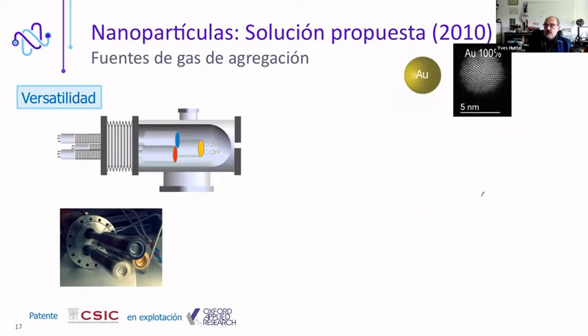But this was too limiting, really. Then we faced the problem of combining different elements inside a single cluster source. That was the first technological limitation we were facing, and we had to find a solution for that. We came up with a solution that consists in replacing the single magnetron inside the aggregation zone with three smaller magnetrons, because the space is limited, in such a way that when we wanted to make pure nanoparticles, we just used one magnetron.